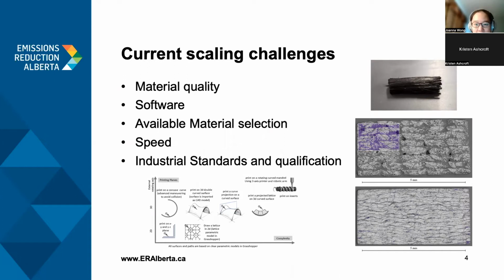Now, highlighted in purple in that slide are the voids of the material. On a typical composite part that has been additively manufactured, the void content is easily in the 40 to 50% range. And there are very well-known correlations between the strength of a component and the void content. Above, say, 2% void content, the mechanical properties of a composite material will drastically decrease. The standard for aerospace components is less than 2% void. So you can see that there's a huge gap that we have to move from additive manufacturing quality down to what is acceptable for an end-use part.